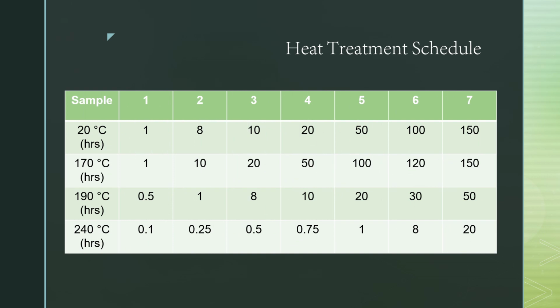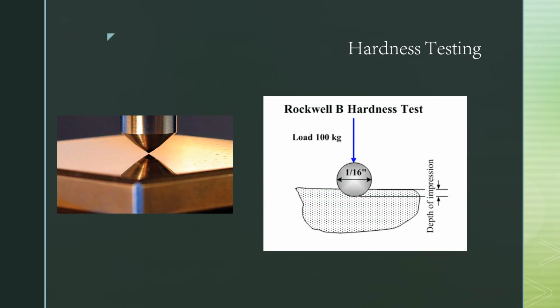I have this nifty resource that can show us holding times for the temperatures we're using. Previous research shows quicker aging occurs at higher temperatures. Sweet! We can test using Rockwell B hardness with a minor load of 10 kg force, major load of 100 kg force, and a dwell time of 5 seconds using a ball indenter. Let's do 10 hardness measurements distributed throughout the central region of each sample. This should give us a good statistical significance.